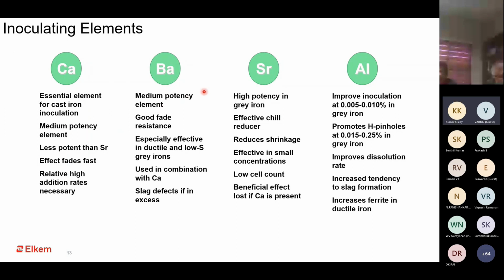Second is barium. In most cases, this inoculant is there in combination with calcium. It's quite a universal inoculant, meaning it can be used for both gray iron and ductile iron, and in fact for compacted graphite iron. So barium has a much wider application range compared to some of the other inoculants. Because the barium oxides that are formed have a much higher fading time, a barium inoculant has very good fade resistance. So the foundries which have a longer pouring time or a longer process time after addition of inoculant, barium is the way to go.